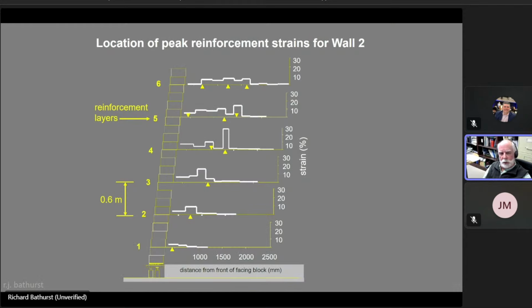And what we were able to do, first of all, at the point of incipient failure, we registered the strains in each reinforcement layer, and that's what this histogram looks like. And then we excavated the wall from the top down, in very thin slices, just as if we were archaeologists. That way we were able to follow the internal failure surface from the top of the backfill down to the bottom of the wall.